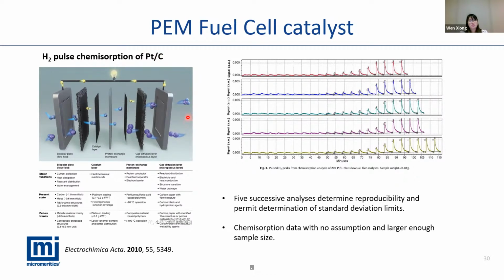This is a very good example of using chemisorption in the PEM fuel cell catalyst. If we look at the right figure, we can see five different kinds of successive analysis were conducted for this sample, as well as some other carbon-supported platinum samples, to determine the reproducibility of using chemisorption to characterize the catalyst.